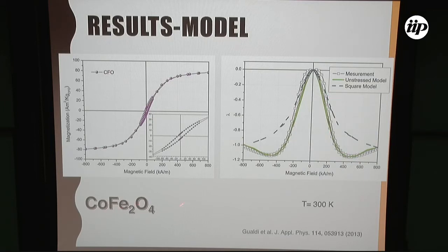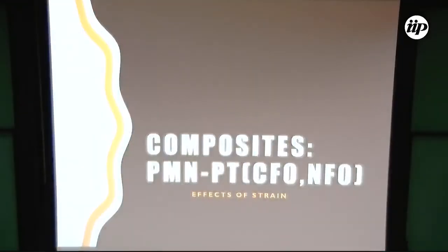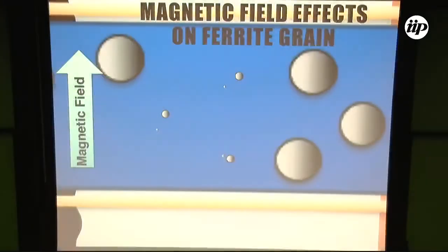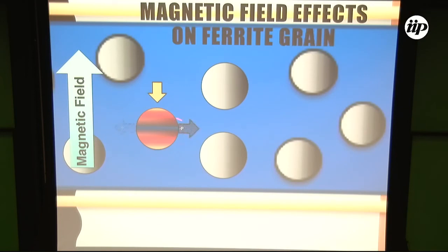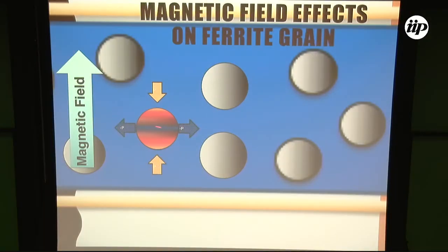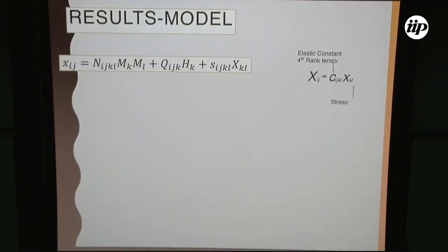This applies directly to the ferrite samples. However, when you apply this effect to this model in composites, it is very important to consider this point. When a magnetic field is applied, the grains of the ferrite change in size and apply pressure due to the environment, the ferroelectric environment of this grain. This changes the characteristic of the magnetostriction of the sample. So it includes one more component associated with the elastic constants, similar to Hooke's law.